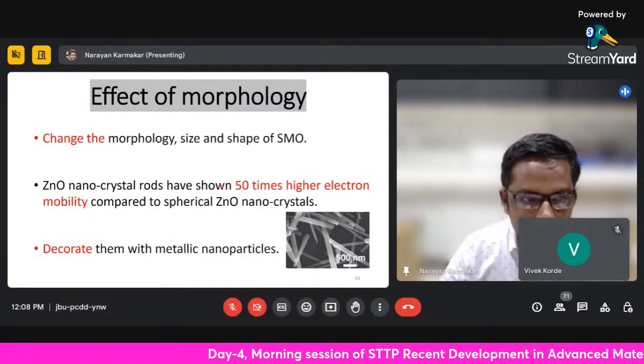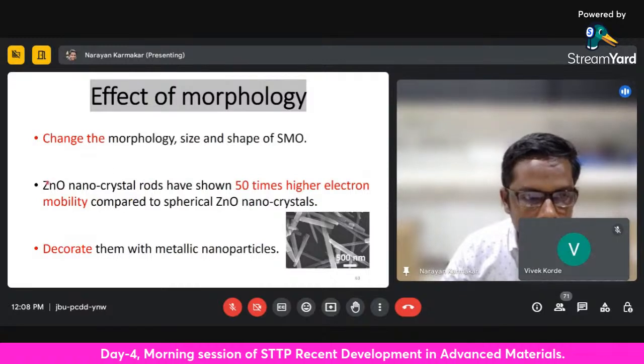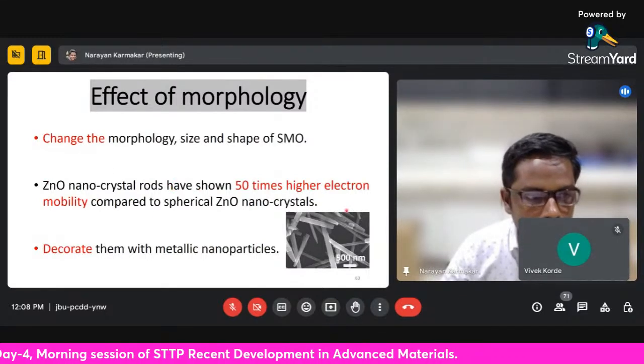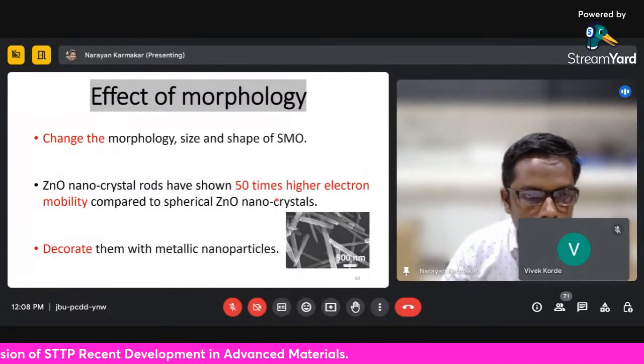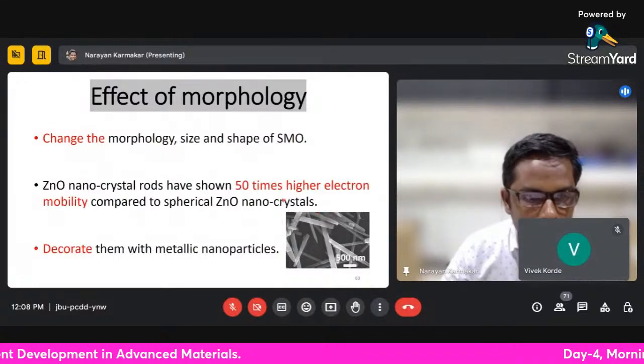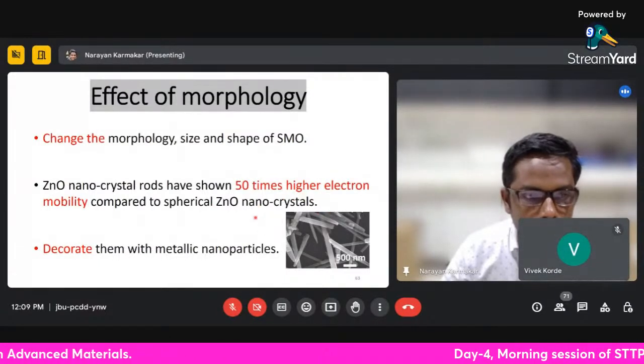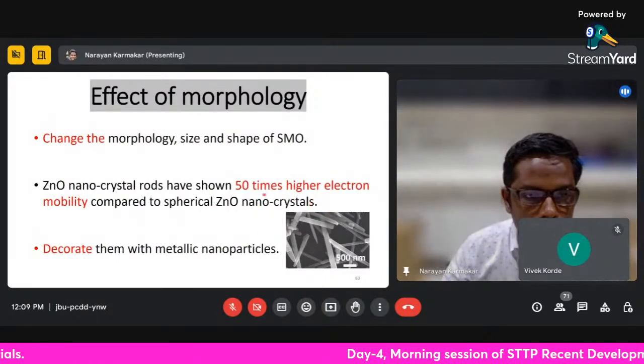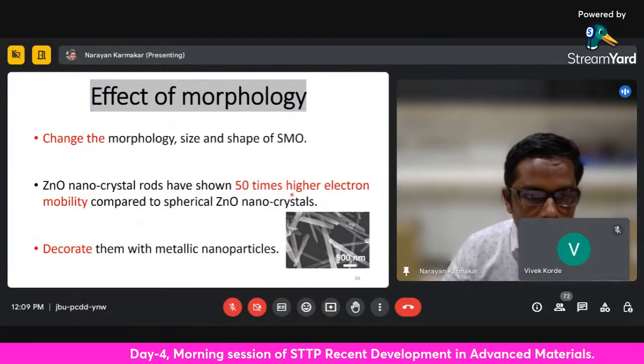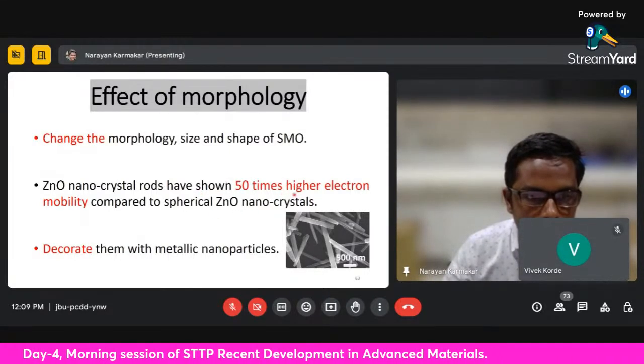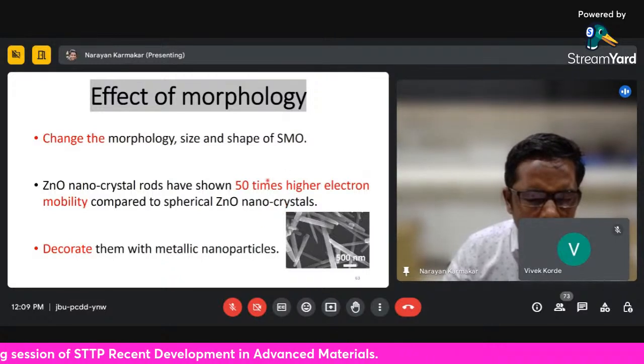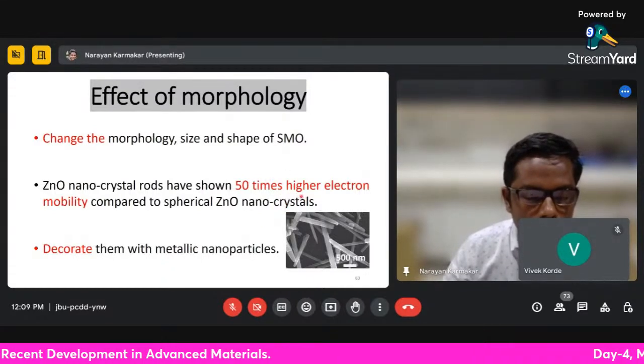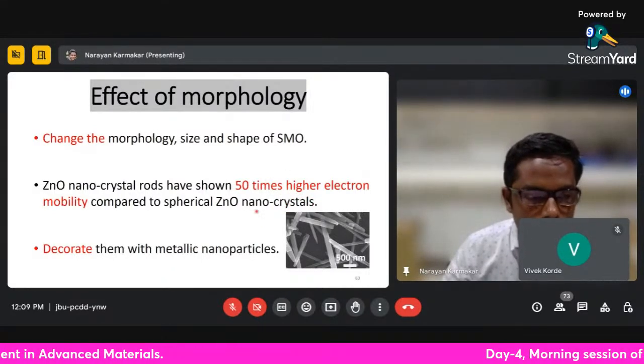Studies suggest that zinc oxide nanocrystal rods have 50 times higher electron mobility when compared with zinc oxide nanocrystals. So what you're doing is making use of this zinc oxide nanocrystal rod, and since because of this high electron mobility, why not make use of this electron mobility of the zinc oxide nanocrystal to improve the sensor response.